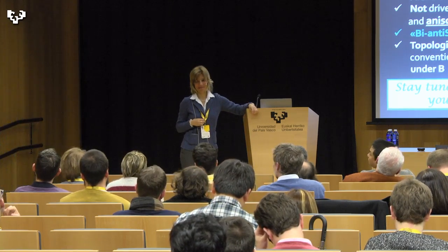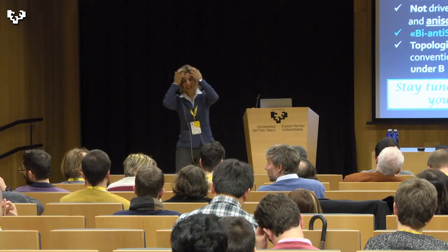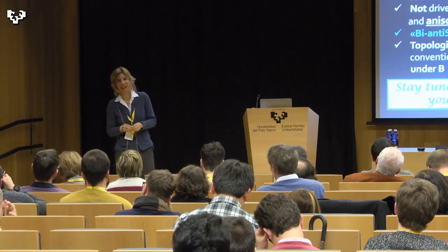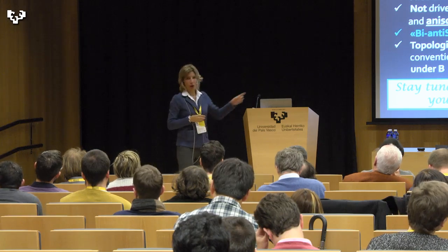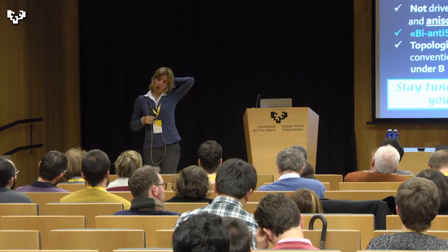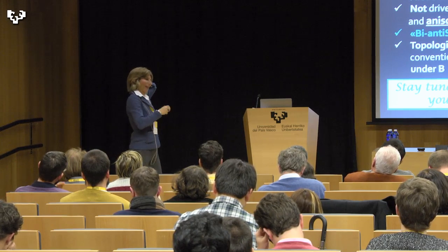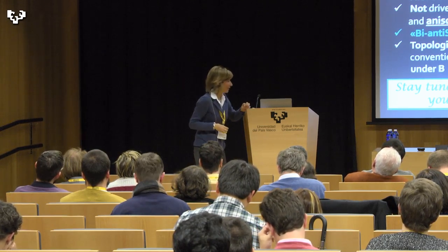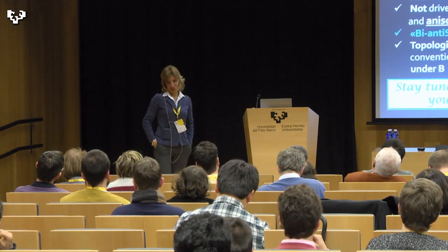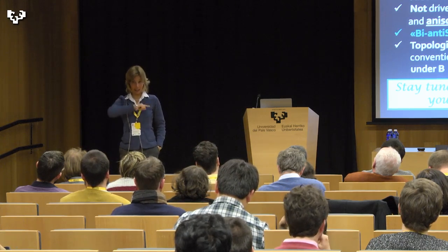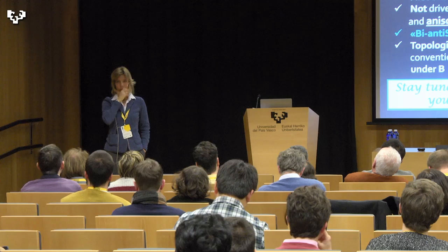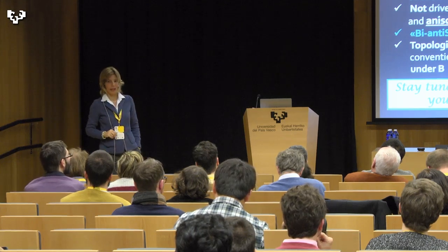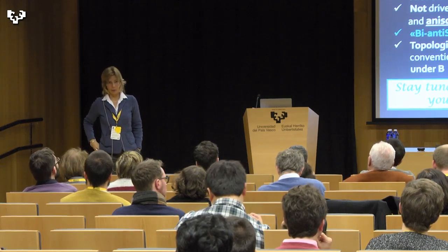So one last question. Regarding your Monte Carlo simulations, what temperature do you do the simulations at? Well, the temperature here, the Curie temperature, or Néel, or skyrmion Néel, I don't know how to call it, is like 40, 50 Kelvin. And the snapshot I'm showing is at 3 Kelvin, so really low temperature.